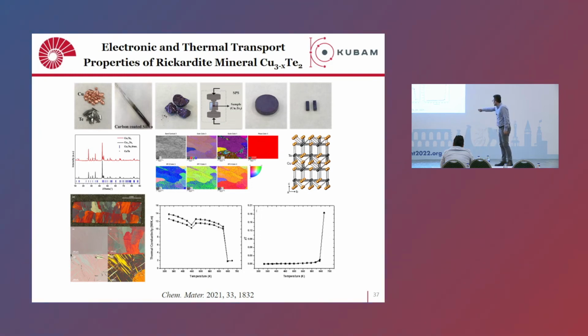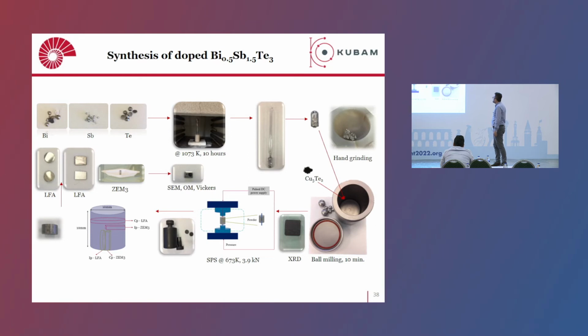And at low temperature, this shows a metallic character, which means here the ZT is almost negligible. And after this transition, you can see that suddenly the ZT goes up quite a bit. Still low, around 0.2, but it is promising. Now, as a copper source, or for its metallic nature, we just put this material in bismuth antimony telluride. So here we prepared the bismuth antimony telluride by solid state synthesis, ground it, put it in a steel vial, added copper telluride, did XRD analysis, SPS, LFA, and all the other analysis, transport characteristics.